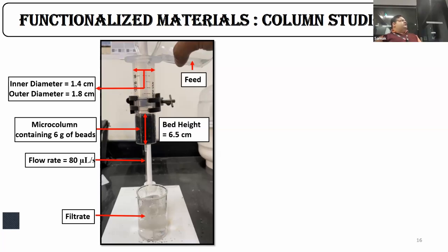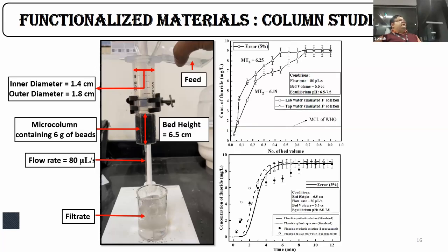We used a flow rate of 80 microliters per second with a syringe that was available with us, and we carried out an extensive analysis for two cases: one with lab water simulated fluoride solution, and the other with tap water simulated fluoride solution.